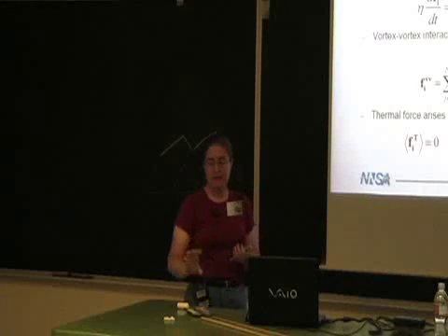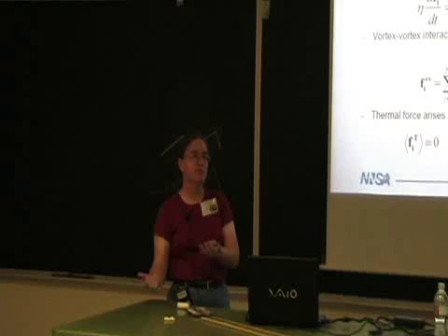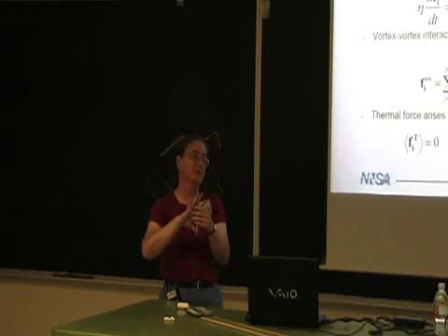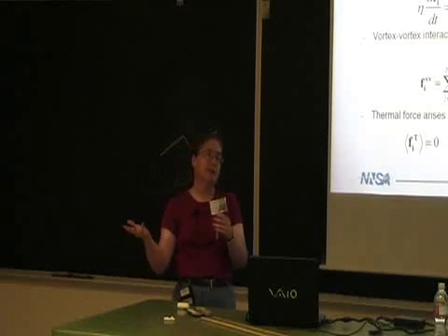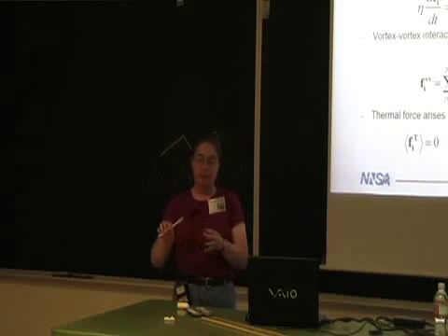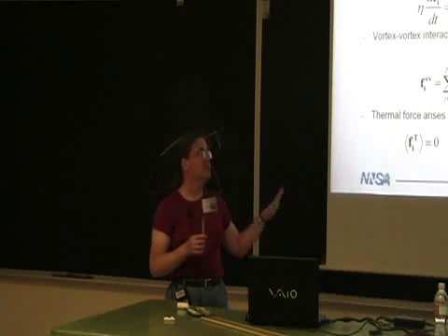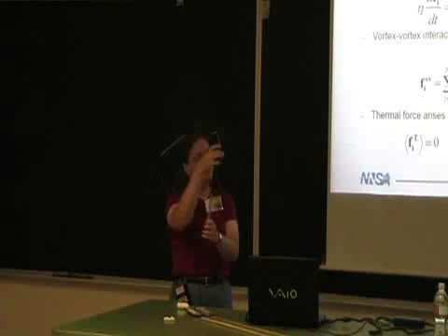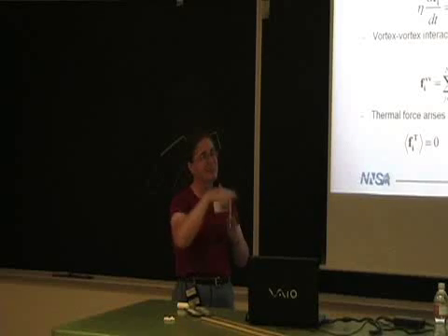Yeah, so the key is in the low temperature materials, thermal fluctuations are so small that the vortex really does stay pretty stiff. I mean, it's got fairly large line tension. But in the high temperature materials like YBCO and especially BSCCO, that's no longer true. You're often running these things at liquid nitrogen temperature, and their thermal fluctuations are definitely significant. So this model becomes not very good, especially for something like BSCCO, where you can actually break this apart into what are called pancake vortices on each line. We could maybe say we're representing one slice, but not really the whole sample.